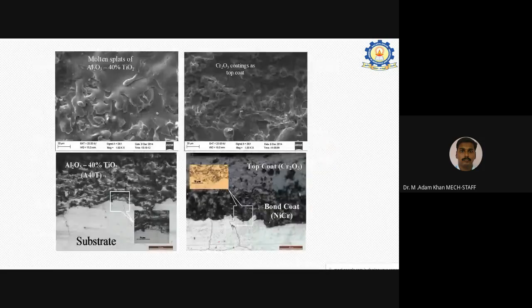So this is the pure surface. You can see how the surface is. These are all called molten splats. You can see the chromium oxide top coat, this one, and this is the bond coat, nickel chromium. Okay, so both have a good metallurgical bonding. So this is from my research. You can refer to my paper if you want to know about this coating.